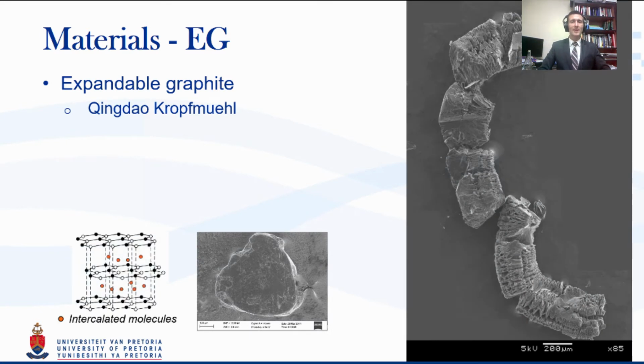What you'll see here is that I took about 15, 20 SEM micrographs of expandable graphite after it had expanded. This gives a very good indication of just how explosive that exfoliation event is. One of the things you'll notice on the bottom left is that the general belief before we started our study was that it would be a pure intercalated material. There'd be intercalated molecules of SO4 interstratified between the layers, and that those would simply release SO2 gas, causing this expansion.